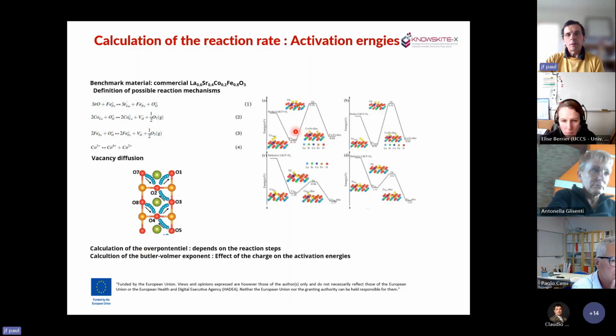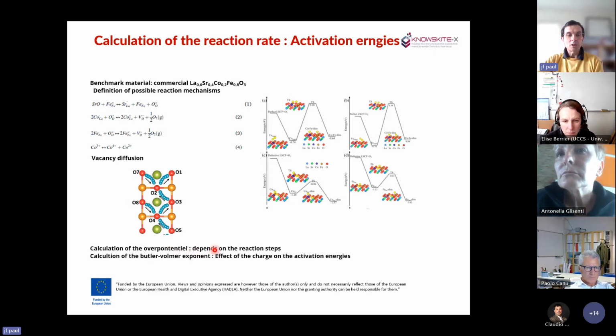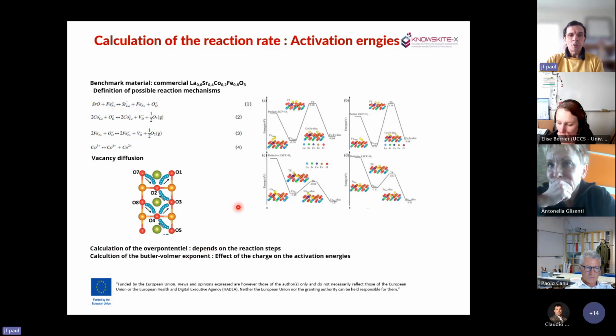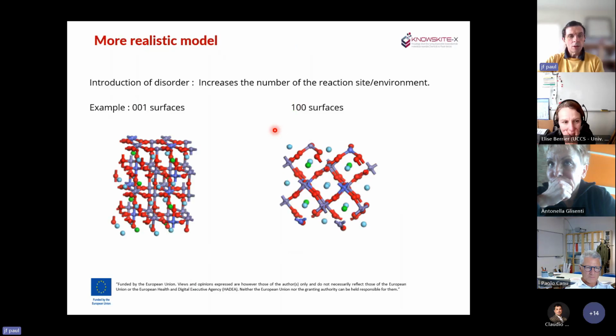Another point that is very important is that this type of calculation can also be done with a variation of the number of electrons. And so it will be possible to compute the effect of the external potential on the activation energy. And this effect of the potential on the activation energy is what is classically seen in the Butler-Volmer equation. It's the exponent that is used in this equation. And this parameter that can be computed at the atomic level can be transferred to a larger scale to the classical Butler-Volmer equation to allow the transposition of the result at the atomic scale to mesoscale. And I think that's all that I want to say now.